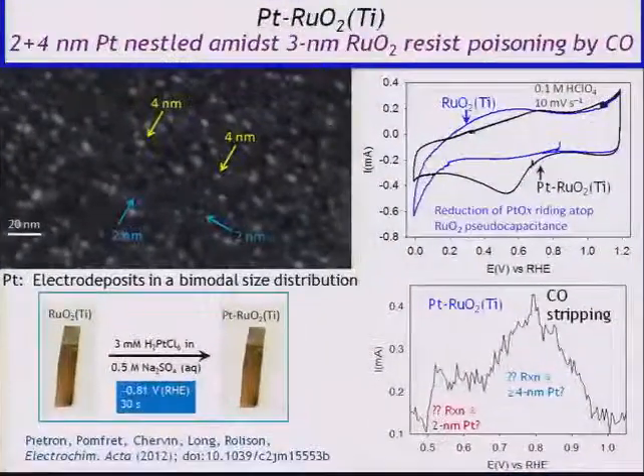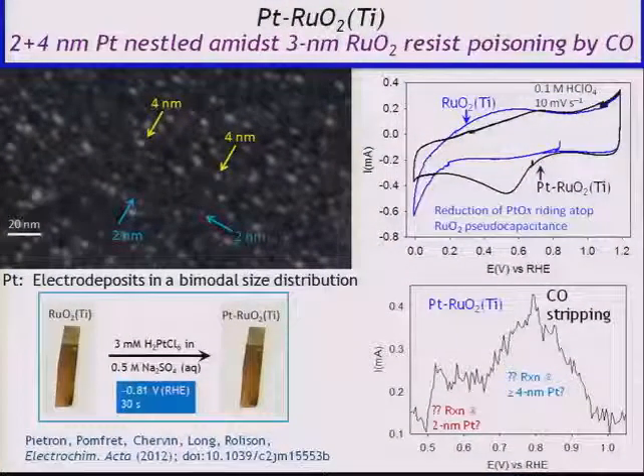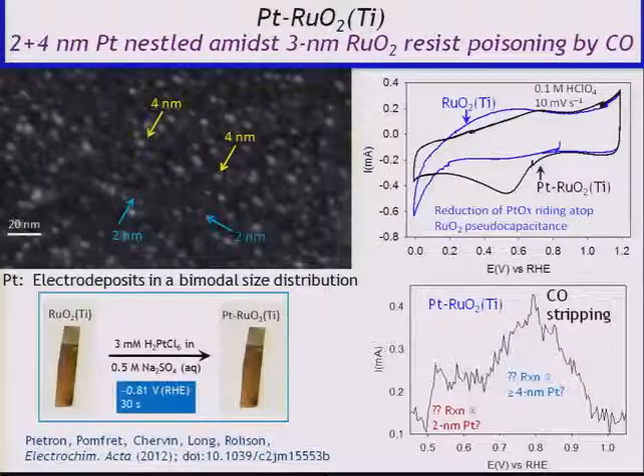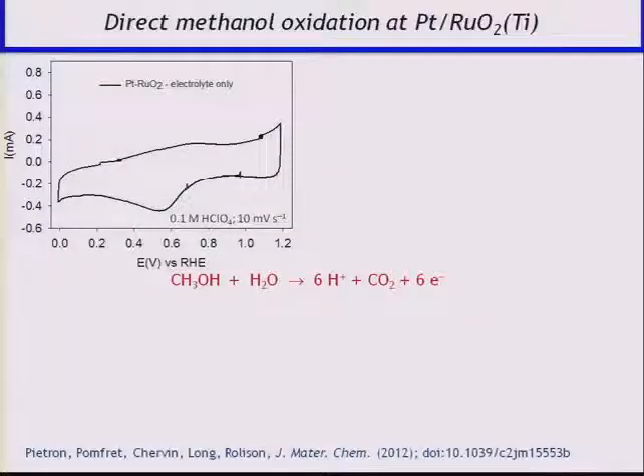And because there are 2 particle sizes there, we actually get 2 peaks for the CO stripping, and the 2 nanometer has one of the lowest CO stripping potentials out there. And that, we believe, is because it is so closely nestled to the ruthenia. So now let's add some methanol.